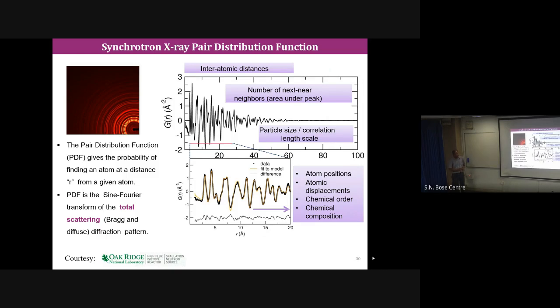So what we do generally, we take very high energy X-ray data and very high Q data. Q is basically the scattering vector, 4 pi sin theta by lambda. So we Fourier transform this high Q data to real space, and then we get G(r) versus r. r is the bond length and G(r) is the pair distribution function. This is a simple concept of radial distribution function in statistics. Okay. So the first peak is basically the first nearest neighbor, the second peak is the second nearest neighbor, and so on. And once the correlation dies down, I can tell the correlation length for a particular compound.